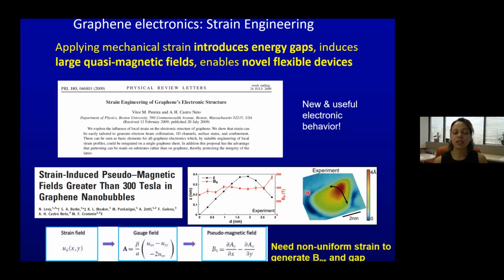Now, I just want to note that a lot of people are interested in seeing these pseudo-magnetic fields, but they do require a non-uniform strain to achieve them. If you look at the strain field, I have a strain field that has an X and a Y component. The strain field enters into the Hamiltonian of the graphene as a vector potential, basically. And because it's a vector potential, you take the derivative of it to get the effective field. So you need something that has X and Y components to it. Only a non-uniform strain will generate these pseudo-magnetic fields. And this also gives you a sense of why the electrons feel like they're in a strong magnetic field. Because when you strain the graphene, the electrons see different phases going in one direction versus the other direction.